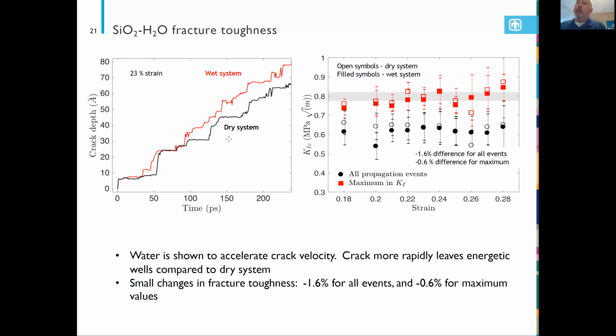But when we calculate the fracture toughness of the wet and dry systems and compare them here, note the open symbols are the dry system, the filled symbols are the wet system. Ultimately, using the two methodologies, we see something somewhat consistent with a decrease in the fracture toughness on the order of about 1%. It's not very significant, but it is a change in the value. So it's interesting to observe that water can play a role even at the atomistic modeling approach.